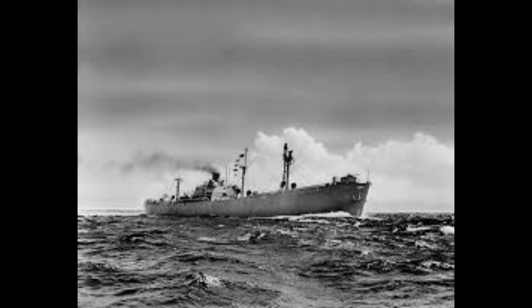The Victory ships used the same steel as Liberty ships, but incorporated design changes based on the failure investigations. Frame spacing was widened from 30 inches to 36 inches, making the ships less stiff and more able to flex with wave motion rather than accumulating stress. The rounded hatch corners and crack arrestor straps prevented the catastrophic propagation seen in Liberty ships.